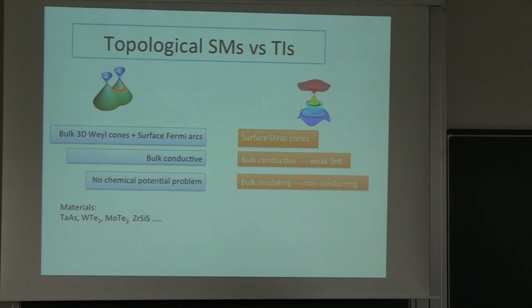And then, here we already know in topological insulators there are several very interesting results using them to build a spin Hall device. And this is what I learned from yesterday. Currently, the problem is the bulk of the topological insulator is too conductive, and this makes the spin Hall very weak. However, if you make the bulk very insulating, this becomes another problem. You don't want the spin Hall material to be too insulating, otherwise the current will go somewhere else.